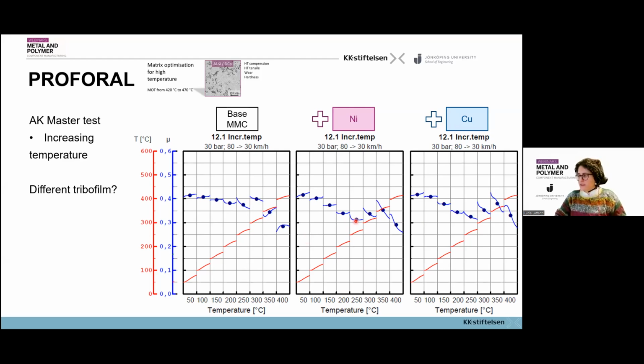So this decrease here before another increase, we will have to further investigate that because we think it might be due to a different tribofilm that gets formed, probably in terms of chemical composition because of the presence of nickel, that somehow has a different behavior at this point, and then gets rebuilt or recovers the performance, goes back up, and then the decrease related to temperature at the end.